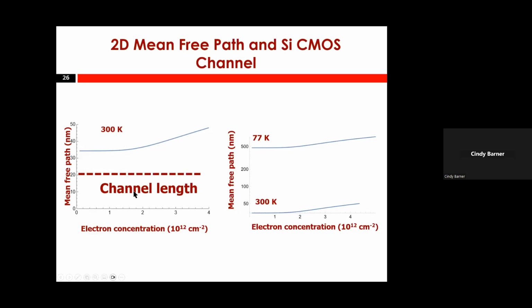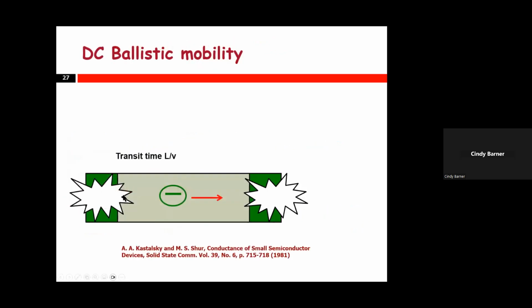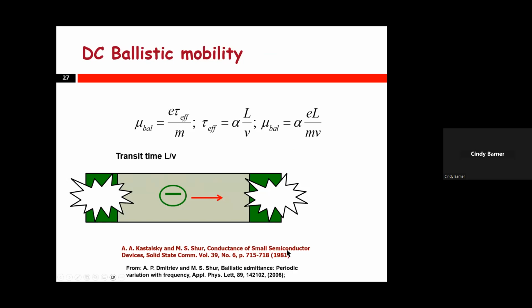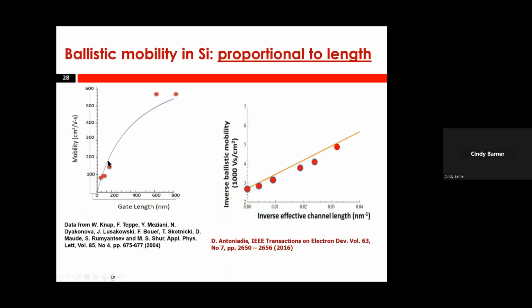And what happens since this scattering? We conclude that actually, well, there is no conventional mobility because it's ballistic motion, no scattering. But there is measured mobility. And this measured mobility has effective scattering time, which is proportional to the transit time. So we come to a conclusion that the measured mobility should go to 0 when N goes to 0. That's, of course, very strong statement. We first made this statement in 1991, and worked more on it, but anyway, only in 2004 we were able to confirm it experimentally.